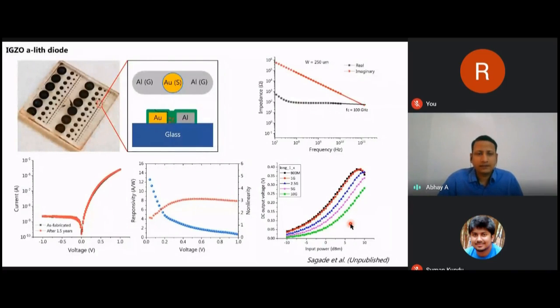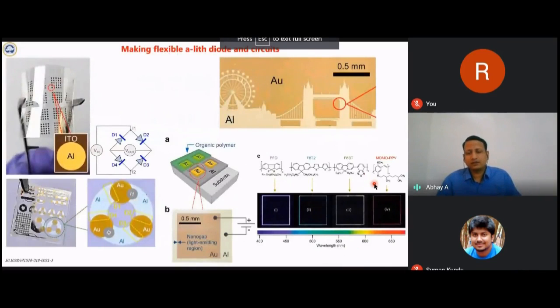We have measured indium gallium zinc oxide diodes also, and they also show intrinsic cutoff frequency of 100 gigahertz and extrinsic cutoff frequency up to 8-9 gigahertz. So this lithography is very versatile, and it can make these patterns not only on a solid substrate but on a flexible substrate also, and we can make rectifier circuits directly, like full wave rectifier circuits, on the chip.